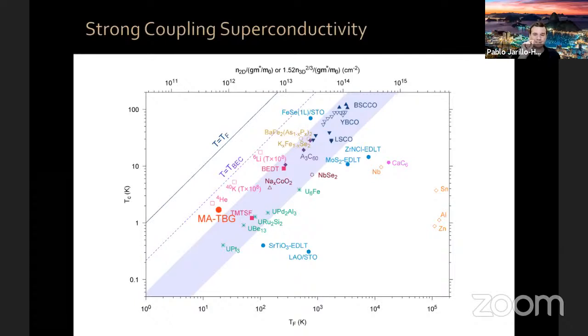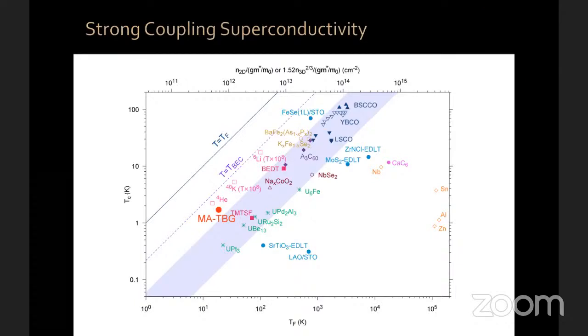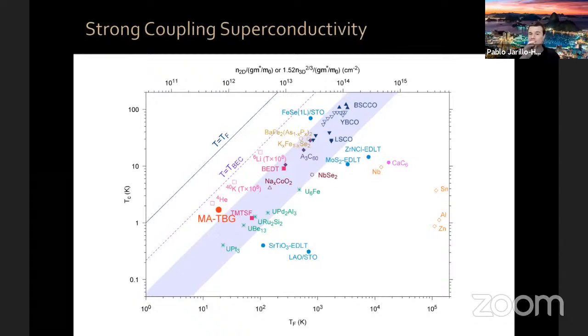And within the flat band, there is a density of states. It's highest in some regions in the flat band, lowest in others. In the regions where the density of states is the highest, the superconductivity is not there. In the region where the density of states is the smallest, the superconductivity is there, okay? So that's the only thing that goes a little bit against the naive BCS formula, the exponential of 1 over the density of states. But of course, once you are in a very strongly coupled regime where the prefactor is important, maybe, and not the exponential, then the situation might change and it deserves very much investigation. Okay, we do not know yet.